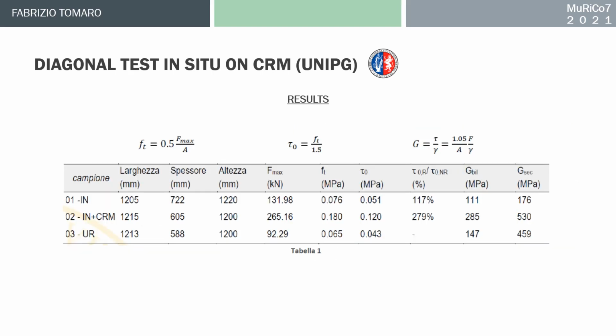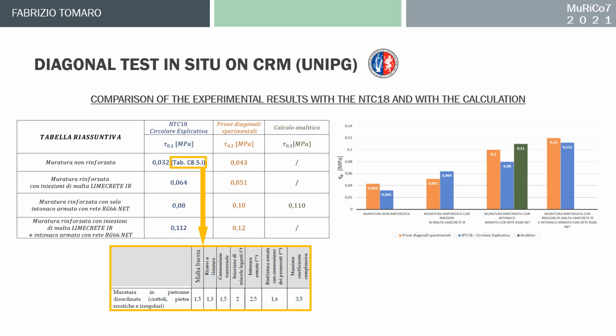The table summarizes the results of the diagonal compression test performed on 3 specimens, showing the ultimate cracking load, the tensile strength by diagonal cracking, the shear strength, and other parameters. It can be seen that the increase in shear strength of the panel reinforced with injection of mortar and reinforced plaster is 279%. The slide shows the comparison of the results obtained following the 3 different calculation criteria adopted for the determination of the average shear resistance of the masonry sample under examination according to the type of consolidation adopted.